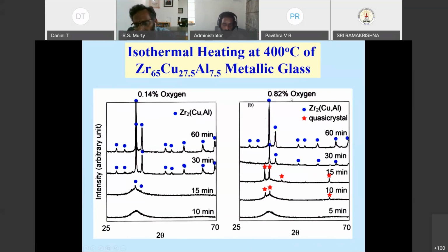Whereas if you take a higher oxygen containing alloy, initially it becomes a quasi-crystal. These 2 peaks that you are seeing belong to a quasi-crystal, and finally this quasi-crystal vanishes and gives you a crystal. And we wanted to know, does it mean that oxygen is stabilizing a quasi-crystal? That was a hunch I had, okay? But unfortunately this XRD will not tell me that.